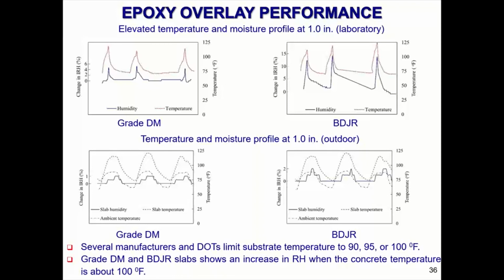So epoxy overlay performance, based on these results, MDOT. Basically what it's saying is that several manufacturers limit their substrate temperatures to 90 degrees or 100 degrees at time of installation of thin epoxy overlay. And it's indicating that we need to update our specification to put an upper bound on the temperature at time of installation, because right now it only has a lower bound in our specification.